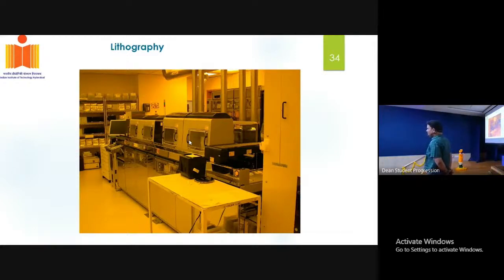So we have the physical vapor deposition technique: thermal evaporation, e-beam evaporation, then sputtering, pulsed laser deposition. Now, how to make the device using this technique? It is not possible to make the device out of this. The moment you deposit the film, it will be a continuous film throughout the structure. If you want to make the nanostructure out of this, you have to use the lithography technique. There exist 2 important lithography techniques, the e-beam lithography and the photolithography.